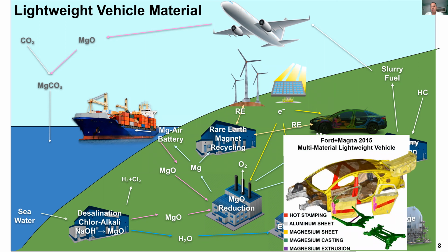We can use magnesium metal alloys to reduce weight in motor vehicles. Magnesium density is just 1.7. That's considerably lower than aluminum. Holding a block of magnesium in your hand feels like holding a piece of wood. Magnesium-intensive auto body can be up to 60 to 70% lighter than steel, and even 20 to 30% lighter than aluminum. This shows the Ford and Magna multi-material lightweight vehicle, which was a design study in 2015, looking ahead 10 years to see what would be possible. And the full vehicle weight is 50% lower than the baseline, which is a 2013 Ford Fusion.